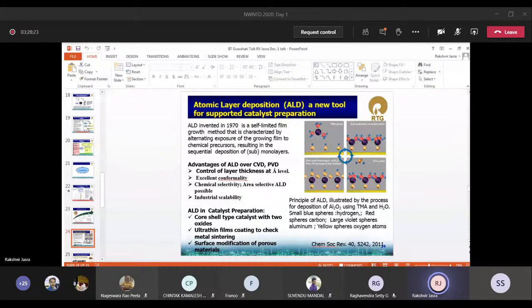How does it help? It doesn't allow platinum and tin to sinter, because the temperature in the reformer is 540 or so. We go as high as 540. So metal movement happens in metal centers. So nanoparticles become bigger particles, and that's how it got deactivated. Second, there is coke formation, carbon formation. So when we put this nano size thin sheet of some metal oxide on our catalyst, it doesn't allow platinum and tin metal particles to coalesce because of sintering, and also the coke formation is less.